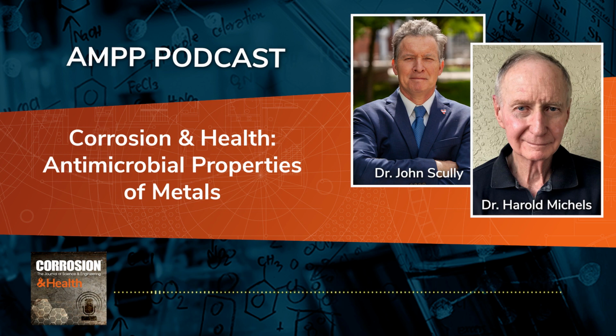And what he found was that, as we mentioned before, the silver seems to work by a similar mechanism, although some of the details are elusive. The silver nanoparticles worked very well. However, silver is too expensive for the communities to afford. And so I really tried to push the copper. And what they found out was that the copper was not as effective as the silver. They seemed to need more copper cations, the cuprous and cupric ions that Harold mentioned.